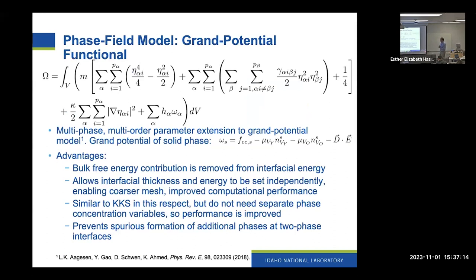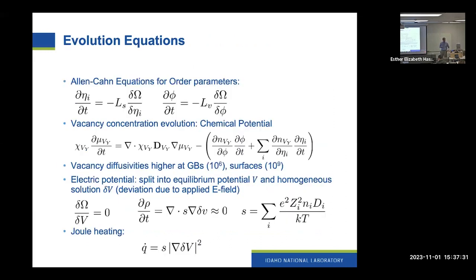Again, we're using this grand potential based model that I described before. In this case, the model formulation is very much the same, except that we have an additional term to account for the interaction between the material and the electric field. So again, we get Allen-Cahn equations for the order parameters, and for the vacancy evolution equations, we have chemical potentials. We didn't have experimentally measured values for diffusivities, but we'll make an assumption that they're higher at grain boundaries by a factor of 10 to the 6 and at surfaces by 10 to the 9. And then we also solve the electric potential concurrently with the evolution equations.